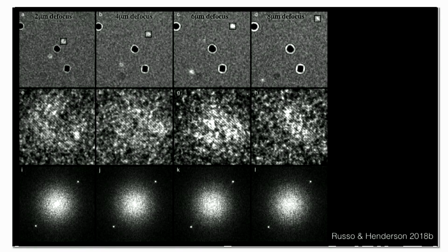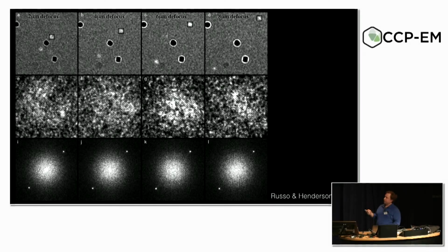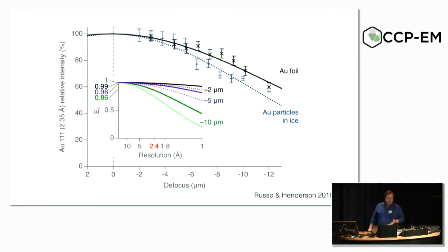And the way we figured out how to quantify it was actually that image I showed you previously, these gold particles. So if you look at these individual images of the lattice, as I showed you earlier, you can measure the power in each of these. And you can measure the power as a function of defocus. Because the further you go out of focus, the more a charge on the specimen affects the angle of the electron wave coming out, the more these should be blurred out, right? If charging were causing a problem. And we thought this was going to be a big problem, actually.